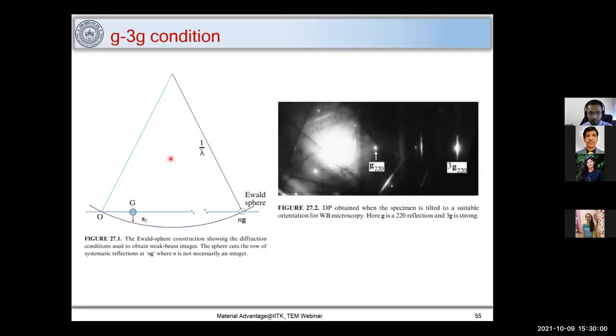Now I'm going towards weak beam dark field conditions, and here I can see that here is a transmitted beam, and here we are talking about G. And now you can see that this G is inside the Ewald sphere. This is an Ewald sphere, and this G is inside this Ewald sphere. That means the excitation error, or this S, is positive. So I mentioned to you that when you want to image a dislocation, S must be positive or greater than 0.